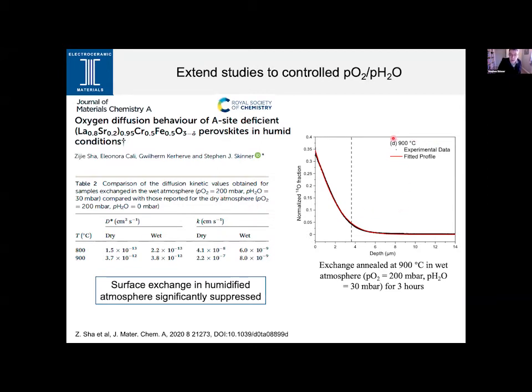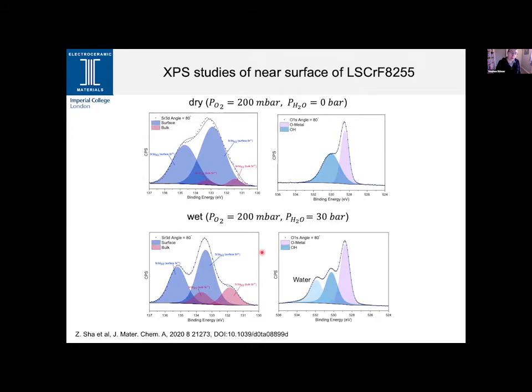Annealing that at 900 degrees C, we can see that we get a very nice diffusion profile again. But what we can also observe in this case, in contrast to the previous study, is that the diffusion coefficients were virtually identical in both dry and wet conditions. Whereas in this case, the surface exchange was notably suppressed. So there's about 1 to 2 orders of magnitude difference in the surface exchange coefficient under that wet oxygen atmosphere. So we wanted to gain some further understanding of the surface structure and how that impacted on these exchange parameters.